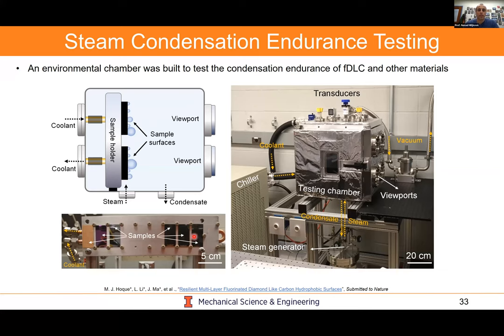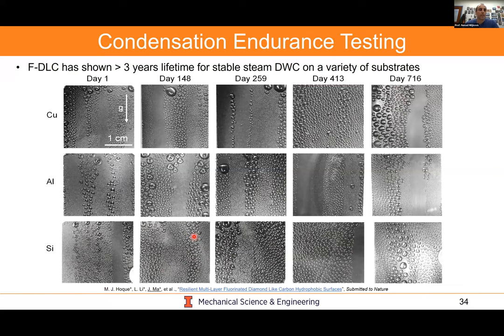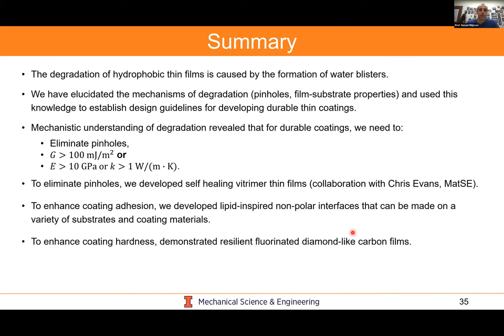And I'll get to the final message. This is a three-year test showing dropwise condensation stability for up to 3 years on copper, aluminum, and silicon. You could see that we've got 716 days here. I actually have to update the number of days because you can see this doesn't quite add up to 3 years. But this is for the paper that we were writing at the time. We've still got ongoing data and we're continuing to do this experiment. We haven't stopped it. It's currently working in lab. So we're very excited by this.